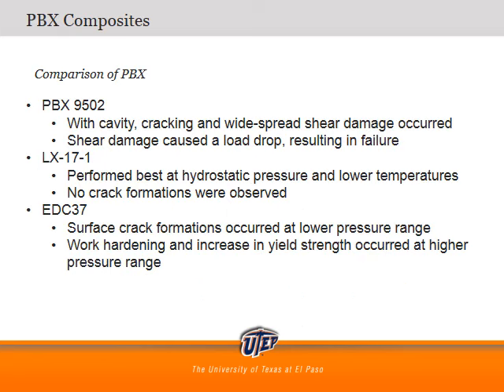In comparing the plastic bonded explosives, PBX 9502 performed the worst. This may be due to the presence of the cavity, which caused cracking and widespread shear damage within the material. The shear damage also caused a load drop, resulting in failure of the component. Further study is needed in order to determine the pressure at which cracking occurs without a cavity.